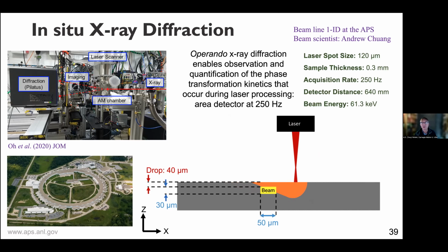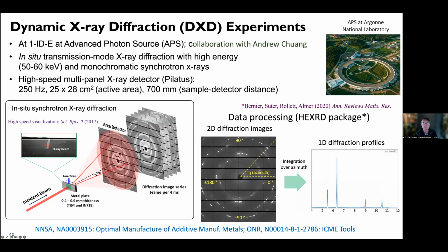And that we run it typically at 250 hertz. And that allows us to capture complete Bragg rings as the melting is occurring, and more crucially, the resolidification of the material afterwards. And so this little view here gives you an idea of what the diffraction patterns look like as they're coming by. And for suitable conditions, then you do indeed see the material melt, diffraction goes away, then it comes back as it resolidifies. And the sort of elementary point is what phases were there before and what phases appear afterwards and at what times. So why do we care about things like that?